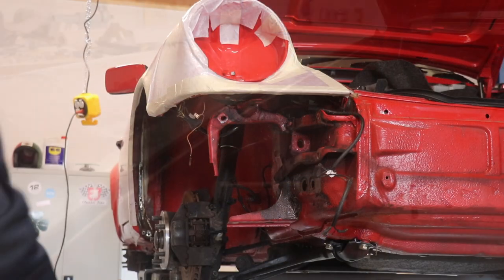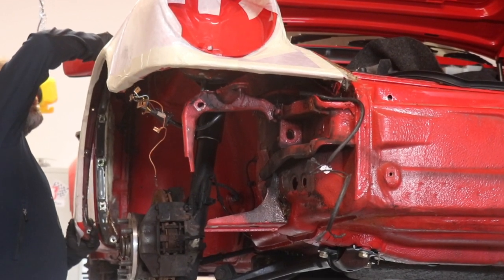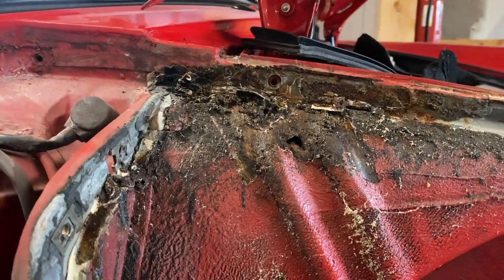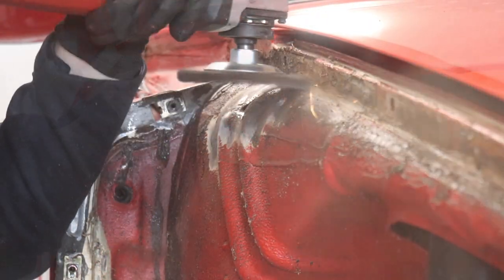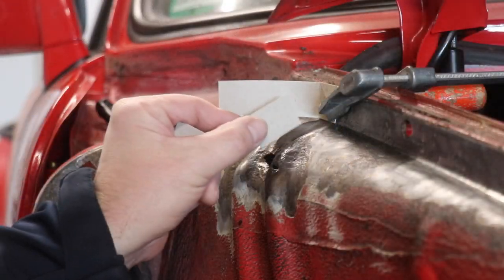If you love cars like I do, I'm sure that to your ears, like to mine, this sounds like cracking bones. I would have never overlooked a rust spot like this in one of my cars if it hadn't been covered in useless filth. So the lesson learned is, the grease stuff belongs in the cavities and not on parts that are permanently exposed to dirt. The one thing that amazes me is how good the backside of this panel looks. The rust really seems to be strictly limited to the very area around the hole, likely because of being galvanized.